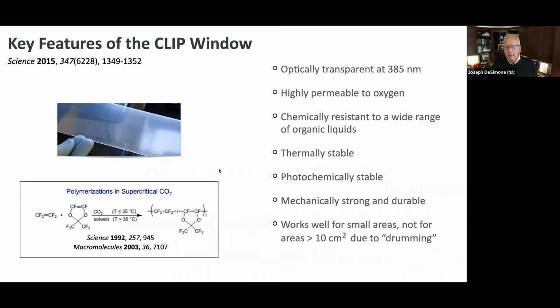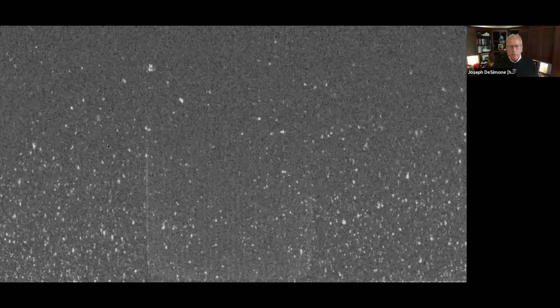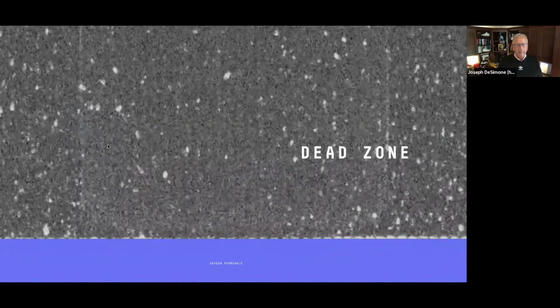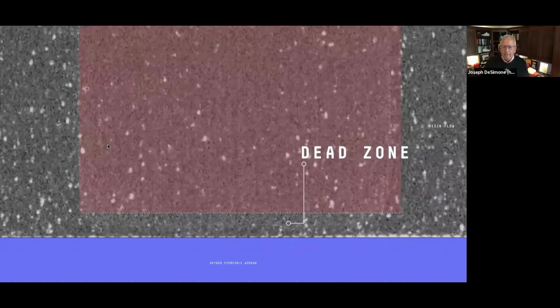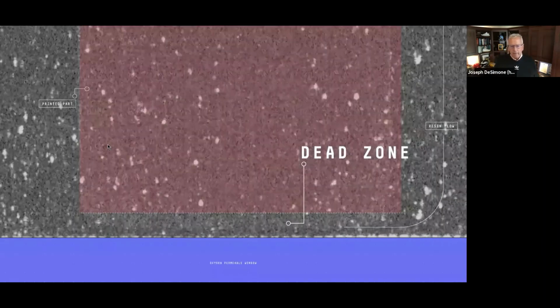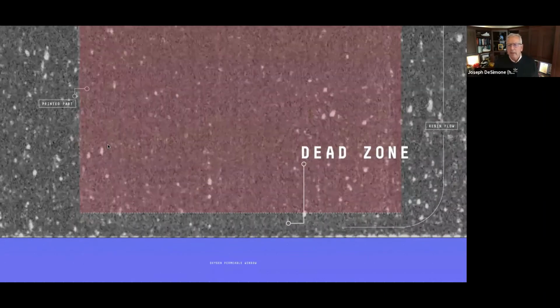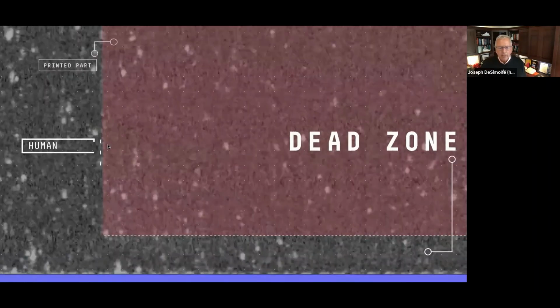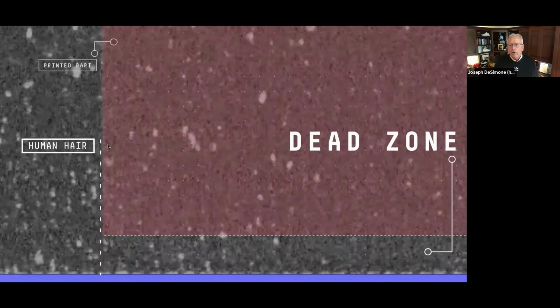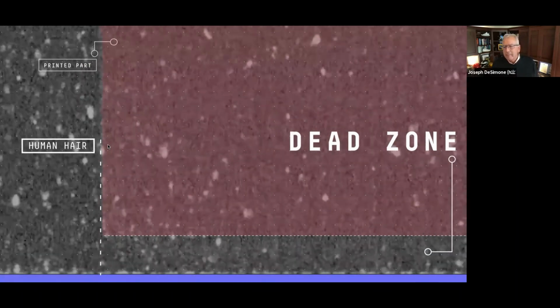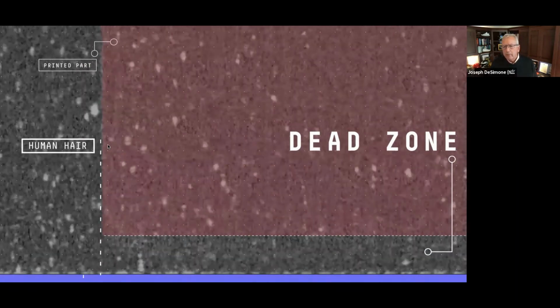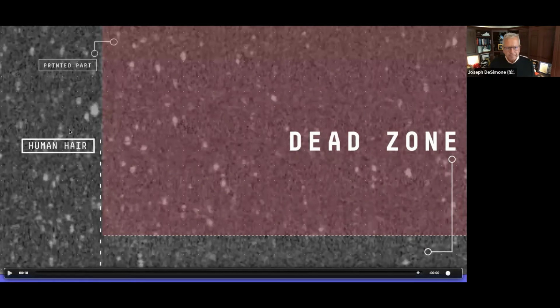it's optically very stable. And so what's happening here is, again, with optical coherence tomography, this pathway, this gap we call the dead zone, is about 20 to 80 microns, depending on the details of how you're running the process. But it allows resin to flow underneath the part and get to the deepest pixel. So it's way more than an adhesion issue. This is a mass transfer opportunity.